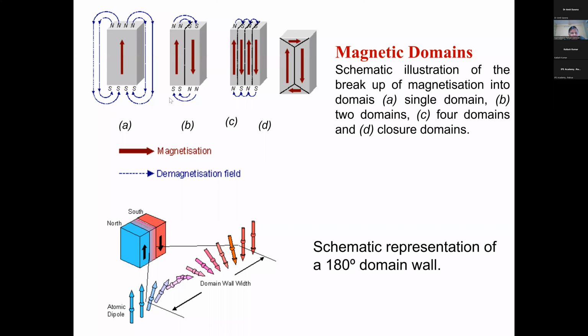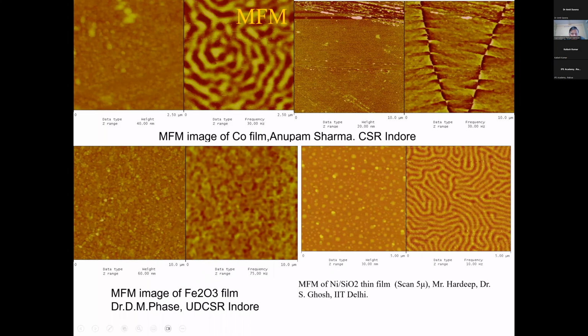And there are various types of magnetism. You can see the magnetism, not only by measuring the hysteresis loop, but also what happens, for example, in thin film structures. In a thin film, its thickness is very small. Domains are very large and they are lateral, parallel to the sample. It's called a cross-tie. Gents used to wear a tie in the collar, not a long tie, a small one, called a collar tie. So it is like this. You can see white to white and black to black. It's like a 180 degree contrast. So these two are very beautiful.